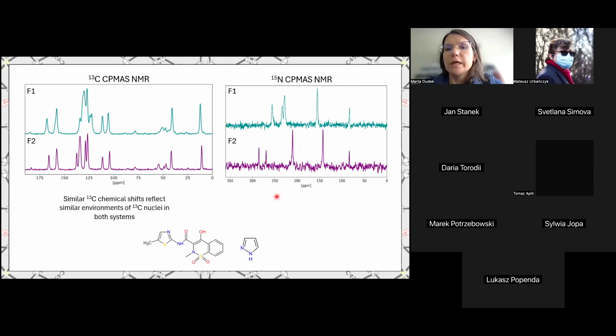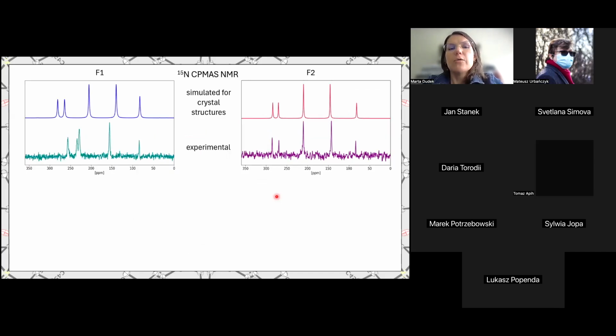This gets us wondering what's going on in the system. So then we calculated NMR parameters, NMR spectra for the structures that we got from the single crystal X-ray diffraction. And you can see that for form 2, the agreement between this calculated red spectrum and the experimental purple one is really good. Nothing to worry about. So we were able in that way to say, okay, this structure is verified by our solid-state NMR measurements. This is that kind of interaction, as you see here on the slide, is actually what we see in real life. But this was not the case for form 1.